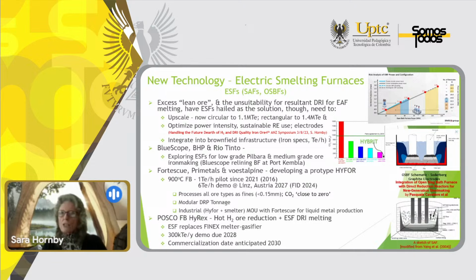The top right-hand chart here shows that currently the maximum on the round ESFs is about 1.1 million tons a year, and for the square ones, it's 1.4. So they're looking to increase the tonnage potential from these furnaces. They also need to optimize the power intensity and look at sustainable renewable energy use. They also have to look at electrodes because currently they are carbon, which is not going to reduce carbon footprint.